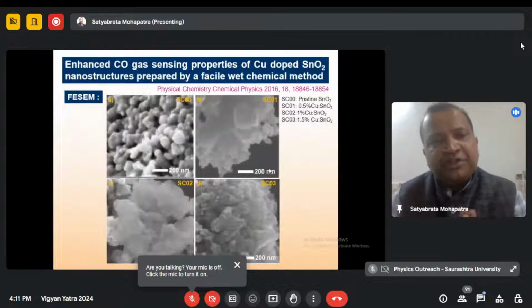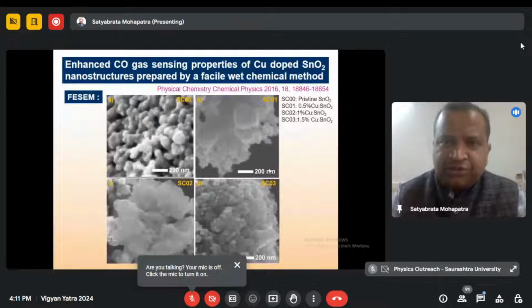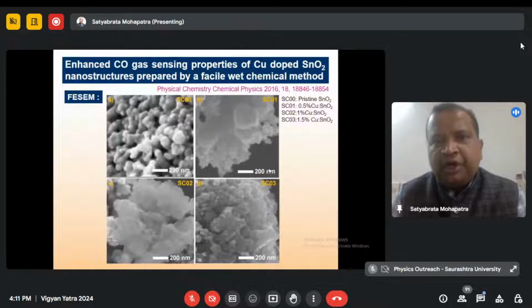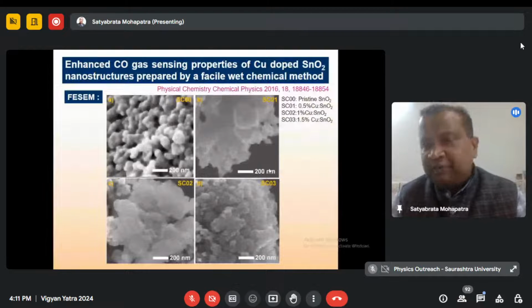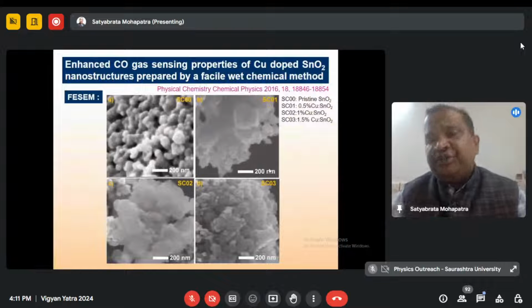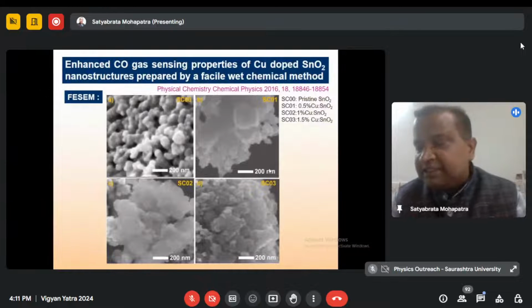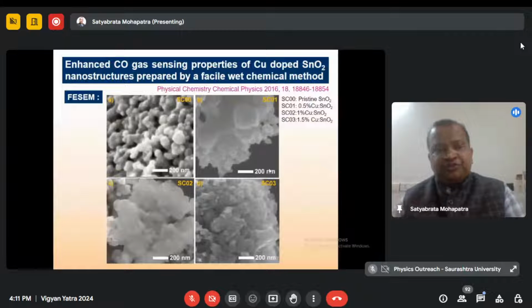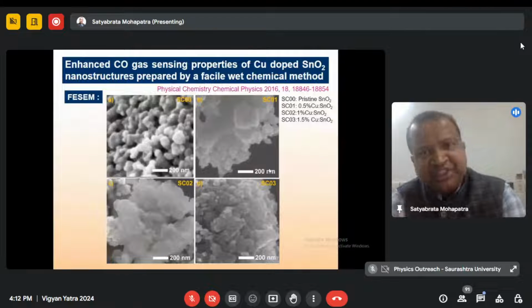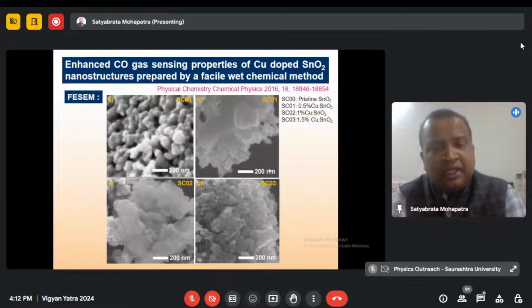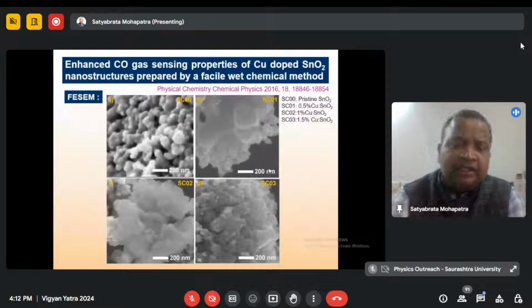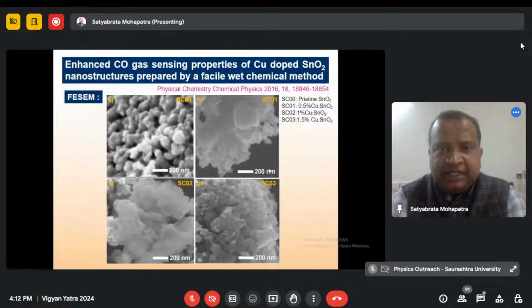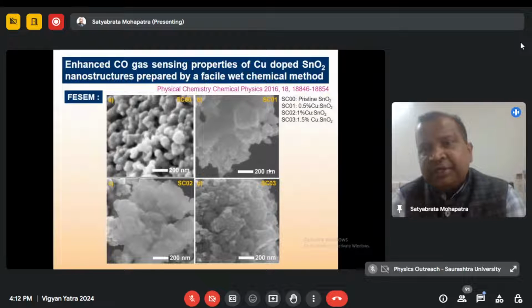So this is one of our works, which was published in 2016 in PCCP, in which we doped copper into tin oxide nanosheets prepared by a facile wet chemical method, and we achieved excellent carbon monoxide gas sensing response. In this, the FESEM clearly shows that there are nanostructures. You can see that SC0 is the pristine tin oxide sample. This is prepared by a wet chemical method, in which we used stannic chloride, urea, and CTAB as a surfactant. What we varied is the doping of copper inside the tin oxide, that's 0.5%, 1%, and 1.5%.